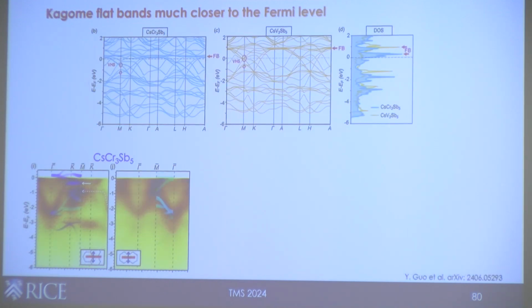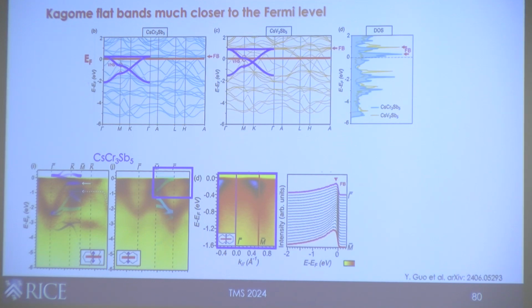So this is actually, yeah, right. It's a promising material. Okay, so what have we done? What can we do? We can look at where the flat band is. By DFT prediction, just to compare, the vanadium one has the van Hove singularities at the Fermi level, and the chromium replacement of vanadium brings the flat band closer to the Fermi level. So this is by DFT, the location of the flat band. When we do photoemission measurements, we can actually see the flat band near the Fermi level. For example, if you take a cut here near the gamma point, it's hard to see in the image, but if you do vertical cuts again, these EDCs, you can see a peak everywhere hugging the Fermi level.